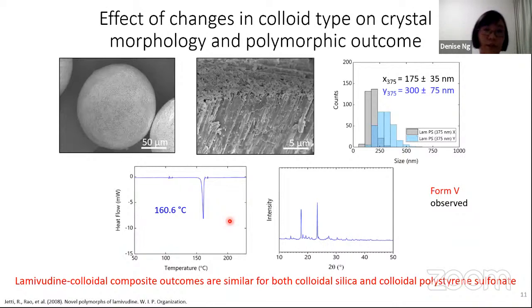Next, to determine if the surface chemistry of the colloid played an impact in the crystallization process, we chose to keep our concentration constant and vary the type of colloid. Here, for interest's sake, we are using colloidal polystyrene sulfonate in our process. We observed that the composites formed at the end are also spherical in nature. In particular, the lamivudine crystals are also fibrillar-like and radially aligned with regards to the droplet periphery. The crystal cross-sectional dimensions in the X and the Y direction are also significantly smaller and narrower in distribution. And the polymorphic form observed in such composites is also form 5, which is identical to that observed in the colloidal silica case. Thus, this suggests that the process may not be influenced by the colloid surface chemistry.